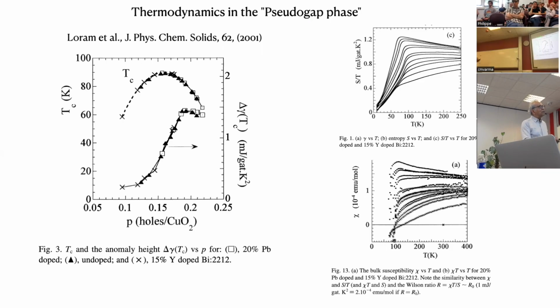This and this are the same. These are deductions from the measurement of specific heat by Loram in bismuth 2212, and you find again S over T, which should be a constant. There is an interesting small increase there, I might speak about, but there's a definite temperature where it begins to change, and in fact, you can put this and this plot essentially on top of each other. So entropy and magnetic susceptibility are behaving similarly.